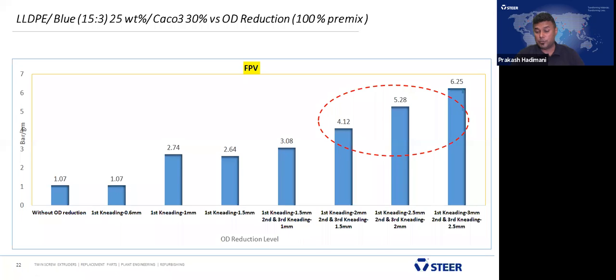The dispersion quality was good. And where you lost the dispersion quality, at the end of the first kneading 2 millimeter, means 1 millimeter per side. Second and third kneading of 1.5 millimeter both the side shows 0.75 per side. The dispersion quality poorer and poorer.